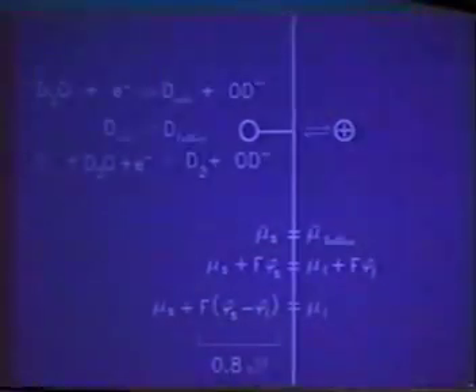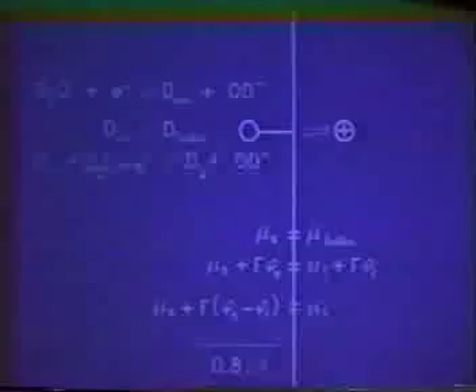It was first done by Frumkin, and this can range from values around 0.8 electron volts. Some reports claim that it is as high as 2 electron volts. So we say, wonderful, that's not very much, but as Professor Yeager pointed out on the next slide, if you were to try to accomplish the same 0.8 electron volt chemical potential by compression of hydrogen in a very simple gas phase reaction, you would have to attain, indeed, astronomical pressures.